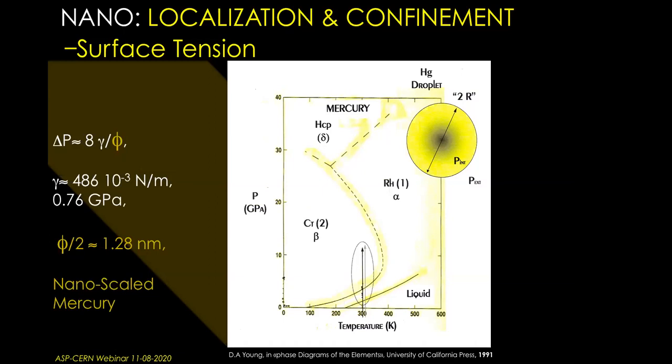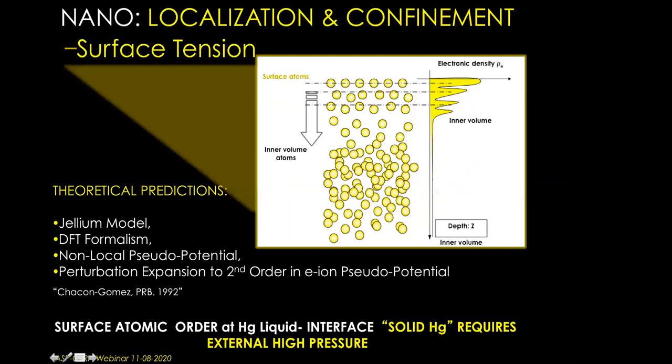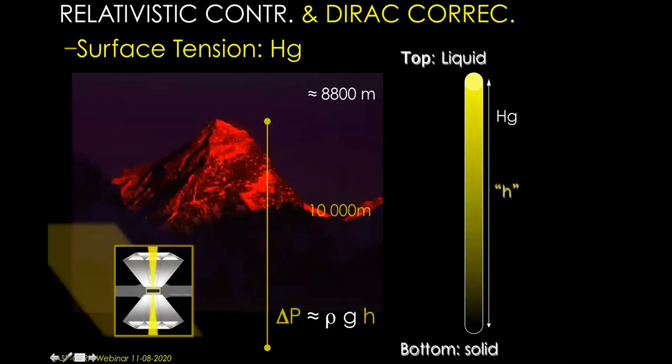Thank you. Now, we know that the pressure that we have to apply on mercury must be 1 gigapascal. Let's go back to our previous graph. We need to have a pressure at the bottom. We have to fill the tube with enough mercury to have the pressure at the bottom equal to 1 gigapascal. And to have that, I need a height H of mercury such that at the bottom, rho G H equals 1 gigapascal. Colleagues, if I do my calculations, rho we know, G is 10, H we have to calculate, and this has to be at least 1 gigapascal.